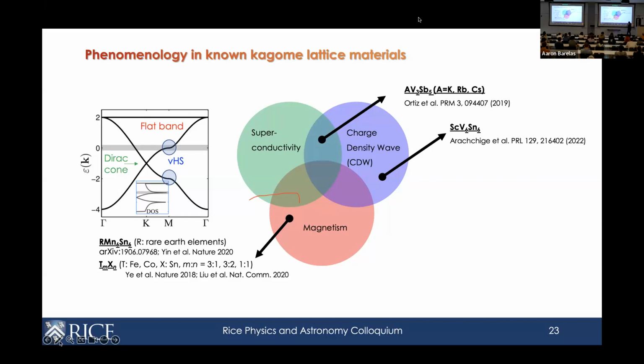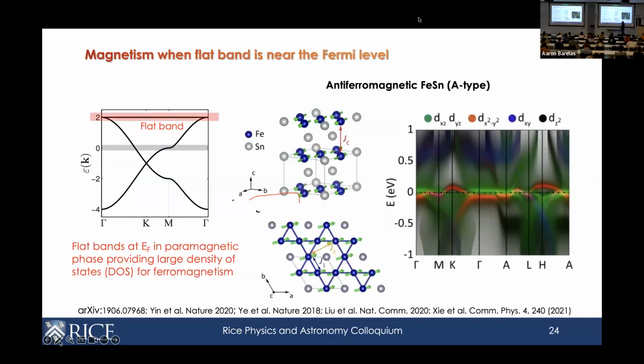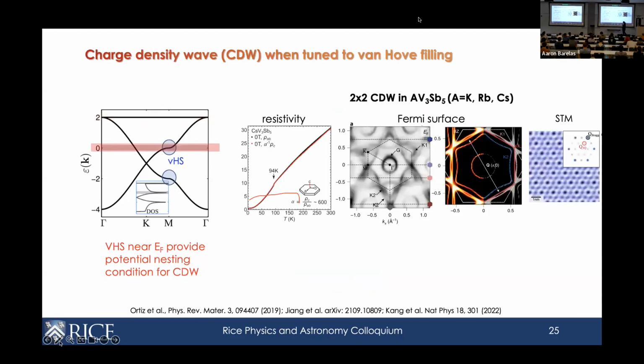Why is that? In a very simple, naive picture, maybe it's the following. For the materials that have magnetic order, they typically have the flat bands where the chemical potential is. For example, this is the compound iron tin, and iron tin is known to have a magnetic order such that the system orders magnetically around 400K. And according to the calculation, you can see this is actually where the flat bands live, near the Fermi level. So this is one class of materials that exhibit magnetism.